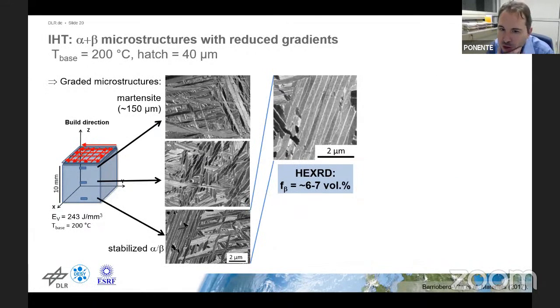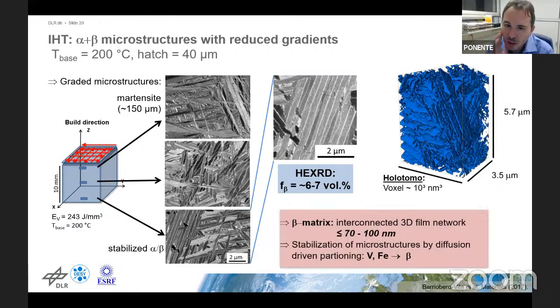Exactly. We've done a little bit of tomography on these materials to try to find out whether these are simply platelet type of beta films or interconnected 3D networks. And we've done that with holotomography in Grenoble at the synchrotron. So a tomography that has a resolution of roughly 10 nanometers, very fine resolutions. And what we found is that we actually don't only have single platelets from the beta phase here, but these platelets are three-dimensionally connected or interwoven. So it's a 3D structure.